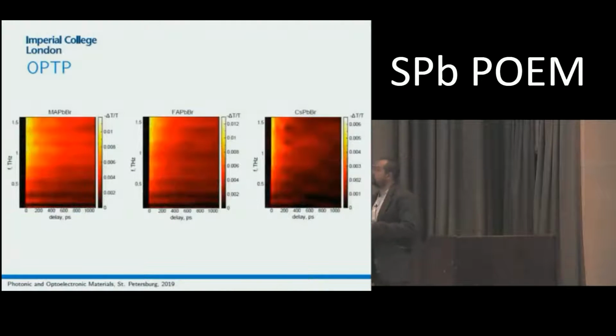And these are the maps that we get. This is the terahertz spectrum. This is the change of transmission normalized to terahertz transmission. So this is the change of transmission that is induced by optical pumping, versus pump delay. We can see that some characteristic frequencies can be noticed in the spectrum, and the characteristic times for some of the frequencies are different from the others. And I will look into this further. This is just preliminary results as they were obtained about a month ago, and we are still looking into the analysis.